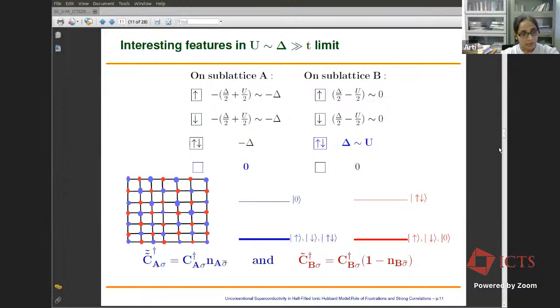The limit of interest, which can give rise to conducting phases in the half-filled ionic Hubbard model, is when the Hubbard interaction U is of the order of the staggered potential and both these energy scales dominate over the hopping term. So let's look at the single site energetics for this limit of the half-filled ionic Hubbard model. As you can see here very clearly, now on one of the sublattices, holes are energetically expensive, but on the other sublattice, doublons are energetically expensive. So if you think in terms of some kind of generalized Schrieffer-Wolff transformation for this model, basically holes should be projected out from your low energy Hilbert space on the A sublattice, and on the B sublattice, doublons should be projected out from your low energy Hilbert space.